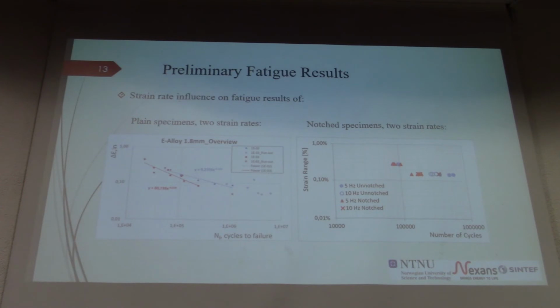So I suspect that there was indeed something going on with the testing, and this was maybe put at a really higher strain range, because we did not see, looking at the fracture, this negative effect of this small notch. So that was probably too small to compete with what is already the fragility of the grain boundaries of these alloys, and there is where we observe the cracking.